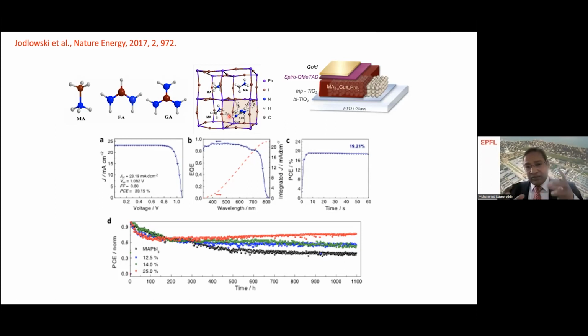So the bigger cation with the 3 smaller cations, they happily sit in the cubic unit. But the cell configuration is, as I discussed before, the same configuration, NIP. Now, if you look at the efficiency data, the black line is the reference sample over 1000 hours. The red curve, with 25% guanidinium and 75% methylammonium, shows extremely stable performance compared to the reference sample. And in between, we have the 14% and 12.5% guanidinium data.